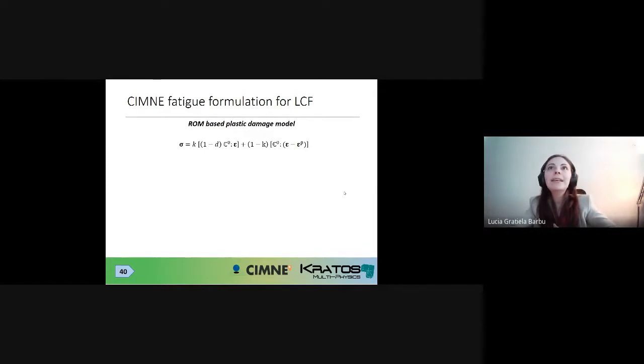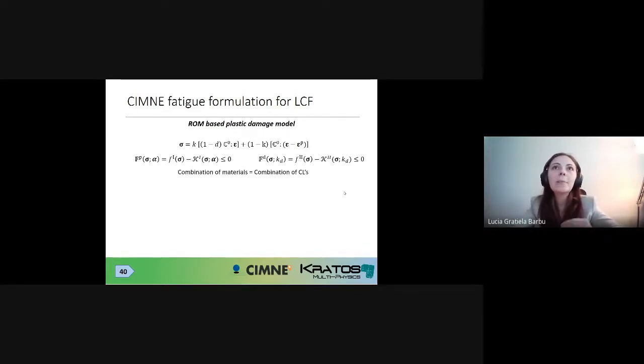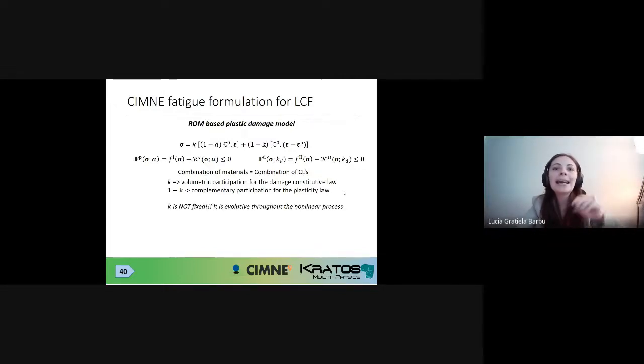And this is very, very interesting and very clever, because it allows you to play with these participations and understand the behavior of homogeneous materials, not as a combination of materials, which was done for composites where you had fiber and matrix, but as a combination of constitutive laws, of constitutive behaviors. And the interesting thing here, as I said, complementary and volumetric participation for the damage and plasticity, is that this volumetric participation is not fixed. It's evolutive throughout the nonlinear process.